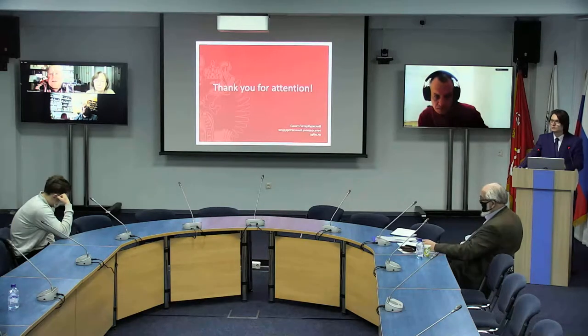The rate and homogeneity of oxygen intercalation into the graphene-cobalt interface is determined not only by temperature and pressure, but also by the crystalline structure of the interface and the presence of defects in graphene. And on this slide, once again, you see all the provisions brought for the defense. And that's basically it. Thank you very much.